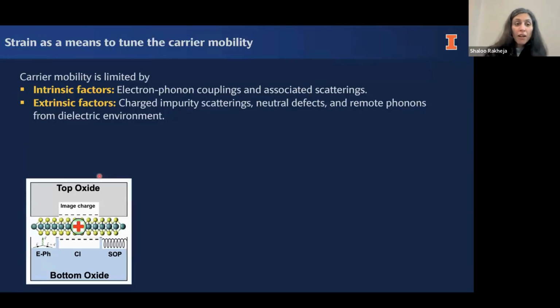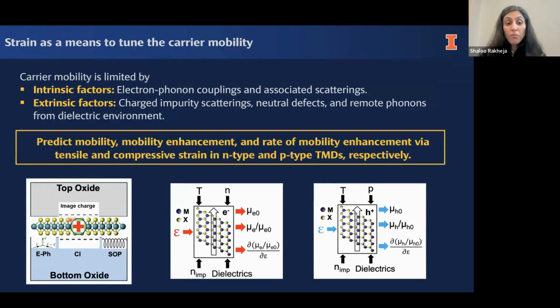So in our group, we have been developing this methodology to define carrier mobility in these 2D materials. In a 2D material, the carrier mobility will be limited by intrinsic factors and also by extrinsic factors. So this is a 2D material, really nice material, but it can interact with the oxide on the top and the bottom. So that's one extrinsic mechanism of scattering of electrons. It also has phonons inside the material. So that's an intrinsic method of scattering of electrons, which will limit mobility.